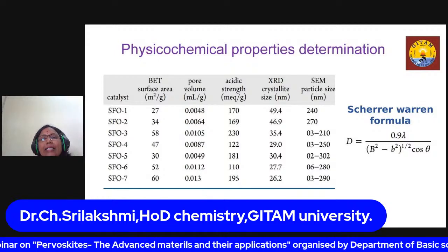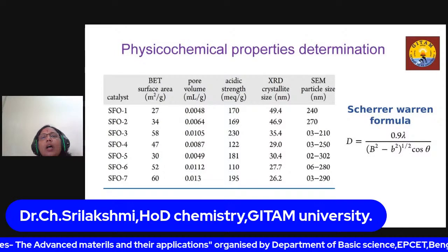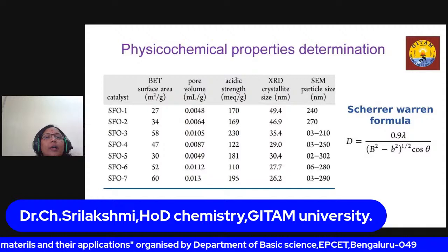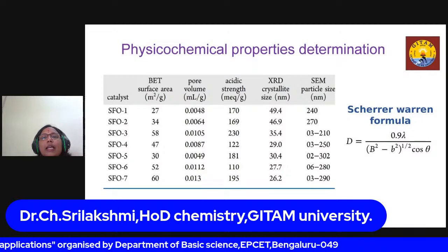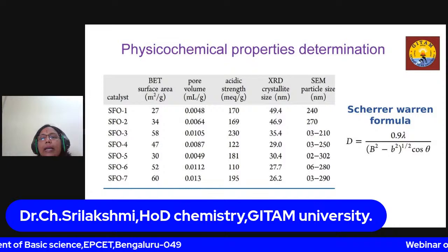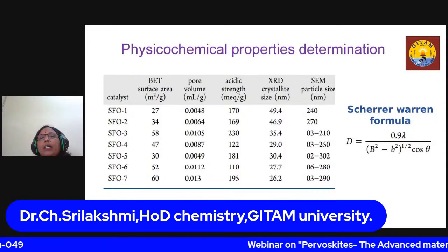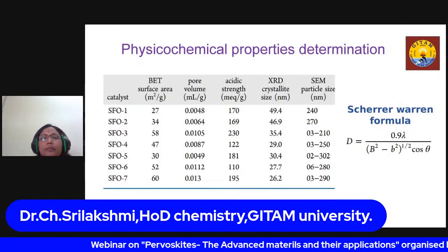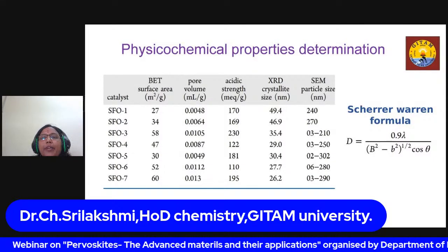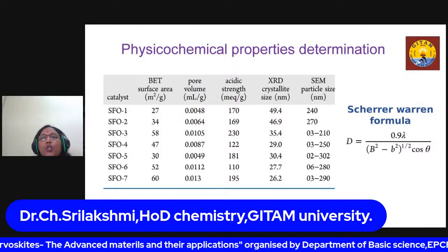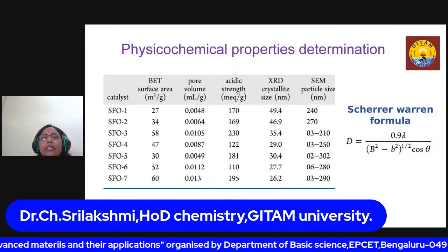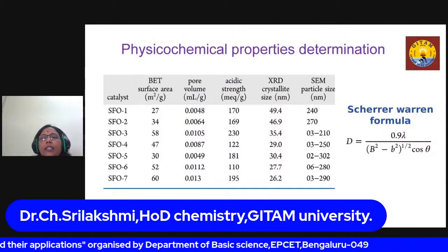What about the crystallite size? Compared to the crystallite size of the individual fuel samples, the crystallite size of the mixture samples is less. The crystallite size, which also means particle size, was also calculated using SEM, and it is between 210 to 302. So this is okay, that is all about it.